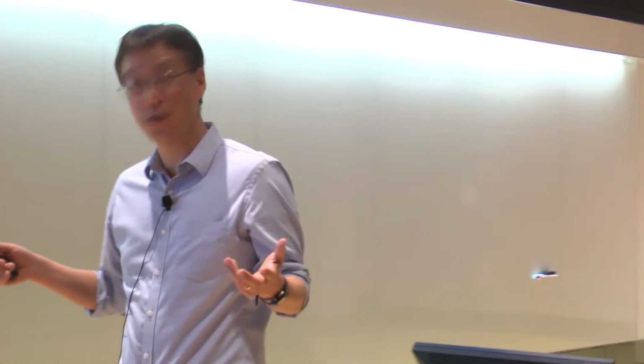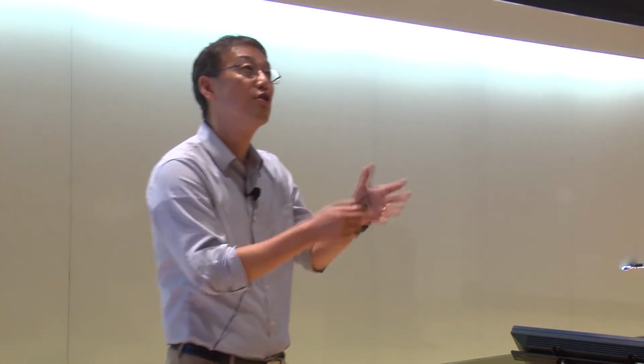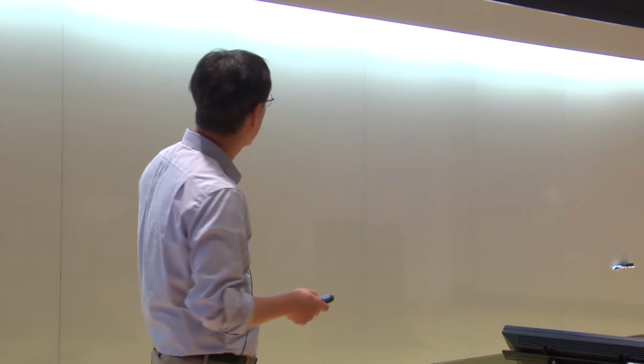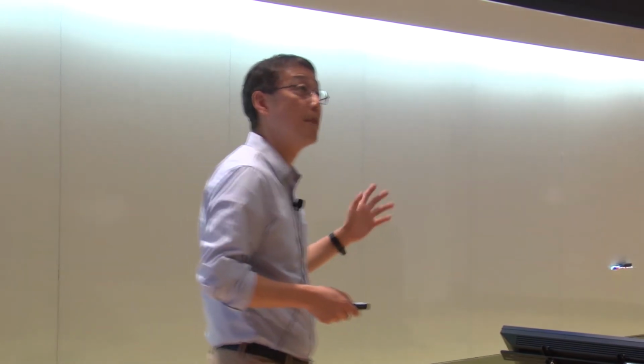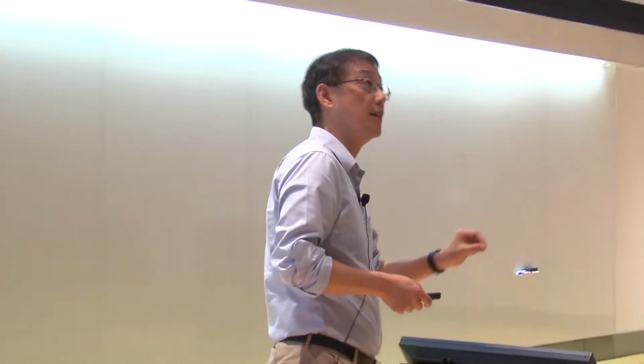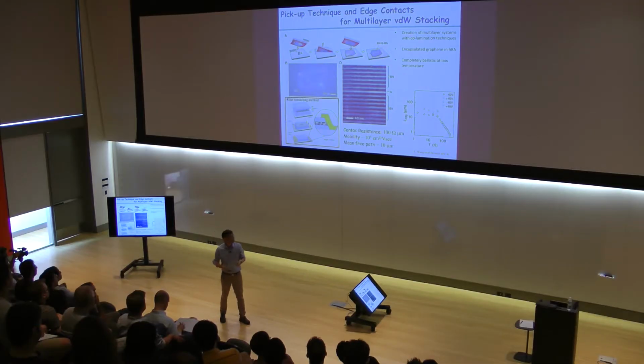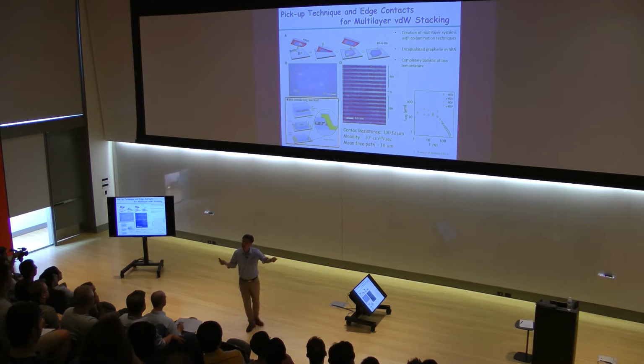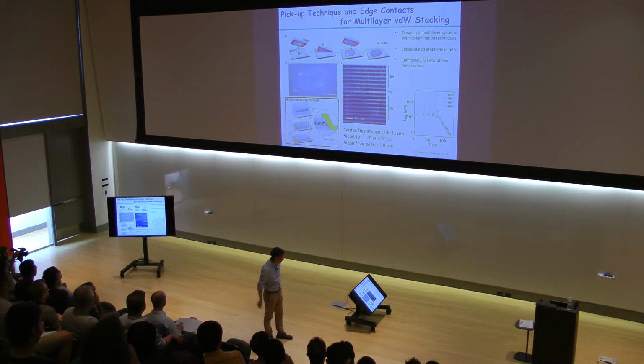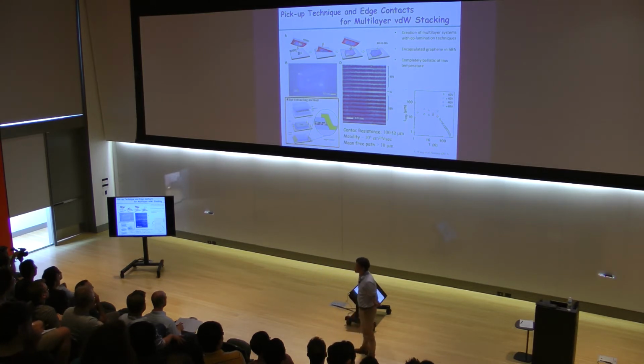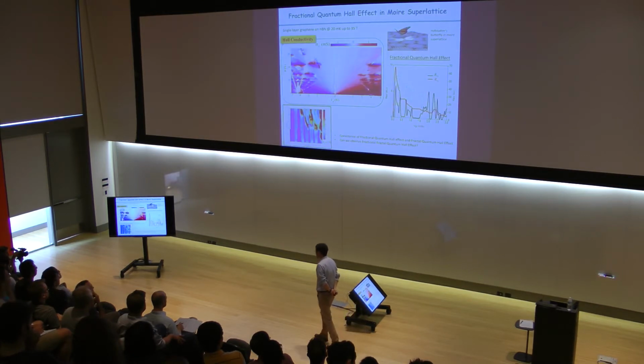So in a sense, you can mimic the semiconductor heterostructures people have been synthesizing using the MBE technique. Here it's a poor man's MBE technique, but nevertheless, it works rather beautifully, especially in graphene. Now we can make this type of device in such a clean limit. The electron mean free path measured in this type of system exceeds several tens of microns. In fact, that electron mean free path is set by the size of the sample we can get, at least at low temperature, which means that we can make an extremely clean interface between graphene and boron nitride. This type of clean sample immediately allows us to do a lot of exciting physics.